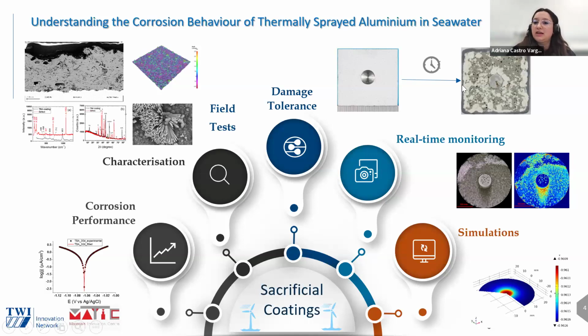So here we can see a coupon with an intentional defect after some time of exposure. At the end, we can see the formation of this white material, which could be aluminum corrosion products or even calcareous deposits, when the electrolyte reaches the substrate. Also, it's clear that the defect of exposed steel is covered by calcareous deposits without any signs of corrosion. So in that sense, we have reported a really low corrosion rate under stagnant conditions.